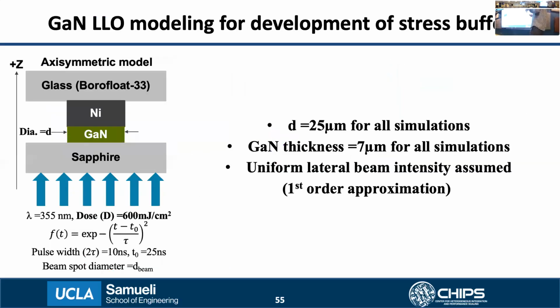Okay. Now let's talk about some of the work we have done to model the LLO process itself to understand the various mechanical stresses that occur in the GaN film. For this modeling, we assumed an axisymmetric model, so the geometry is cylindrical, with the sapphire at the bottom, the GaN, then a nickel layer on top of the GaN, and finally the glass. The laser is shone from the backside of the sapphire substrate. In our experiments, we use a 355 nanometer wavelength, where the incident dose of the light was around 600 millijoules per square centimeter. Because the incident light was from a solid state laser, its temporal intensity profile is also Gaussian, given by that expression, with a pulse width of about 10 nanoseconds, and the peak of the pulse occurring at 25 nanoseconds from time t0 equals 0.